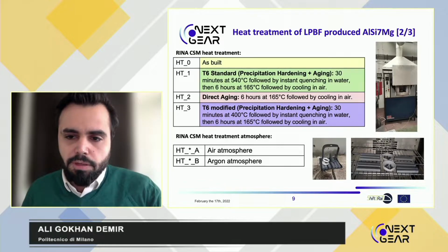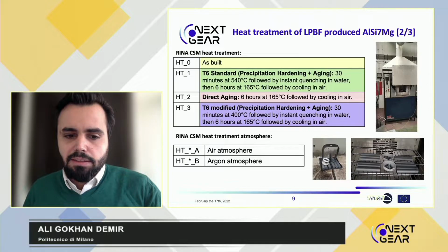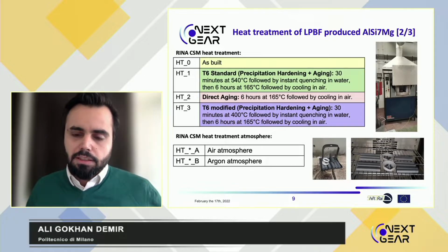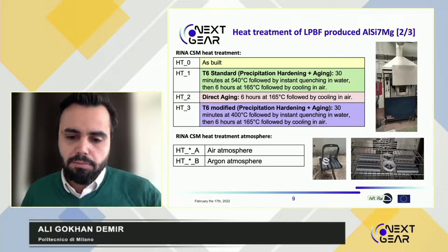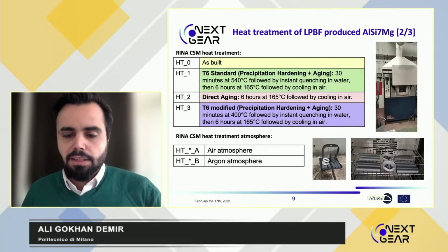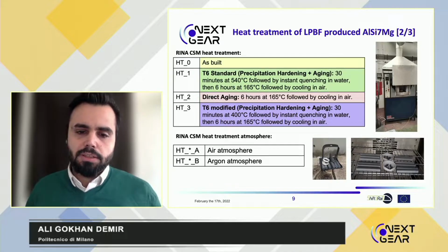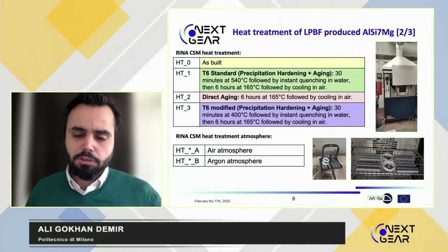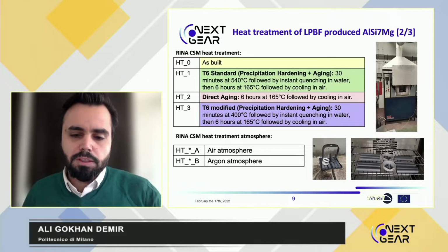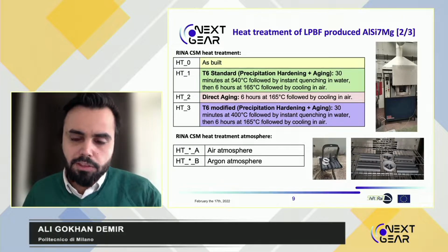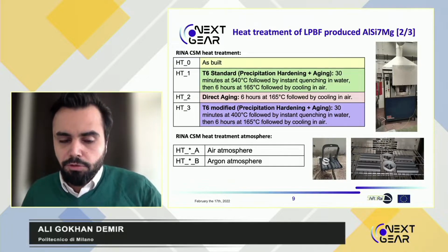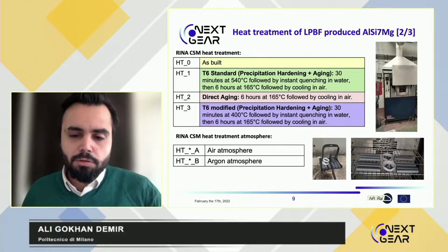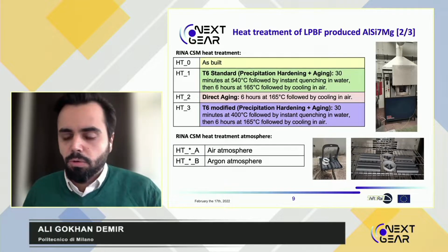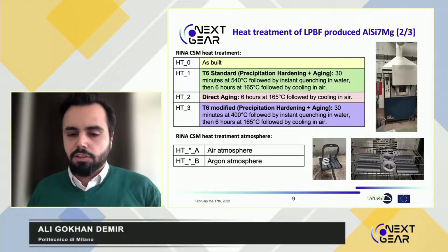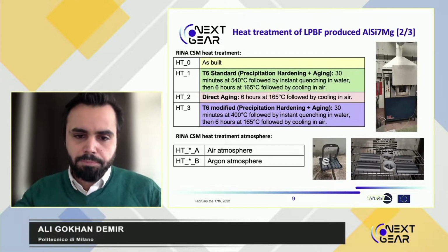You can see the process parameters in detail, but the idea is that we were aiming for adequate mechanical properties, but also trying to figure out a way that we could make the whole heat treatment process easier for a decentralized manufacturing. For that reason, we also considered whether we can reduce the gas consumption during the heat treatment, whether we can do this in air atmosphere or in argon atmosphere, which would potentially increase the costs of the heat treatment.